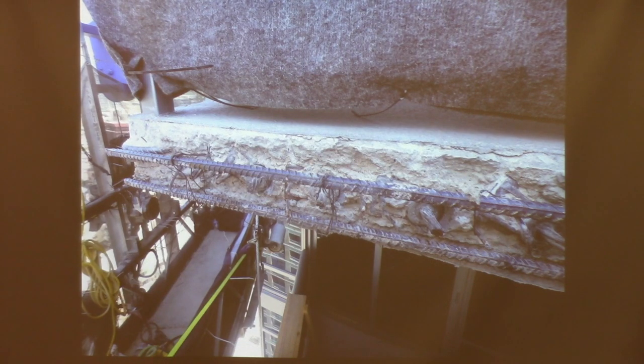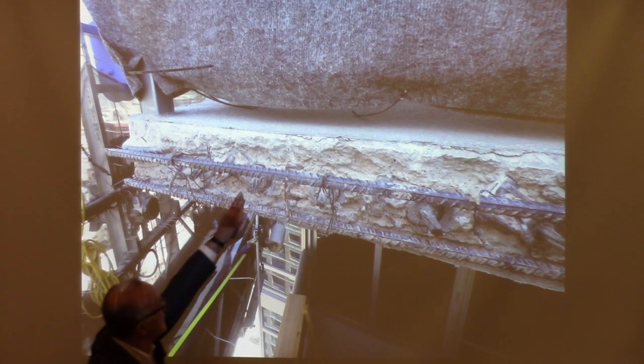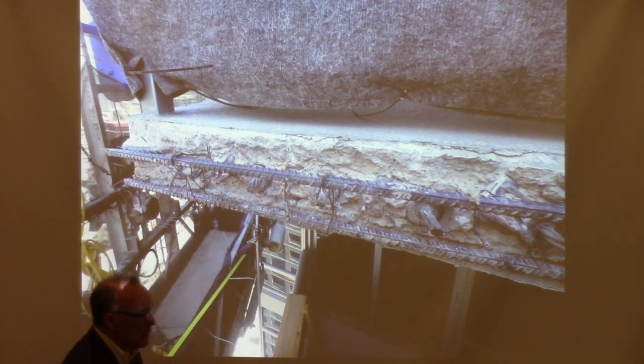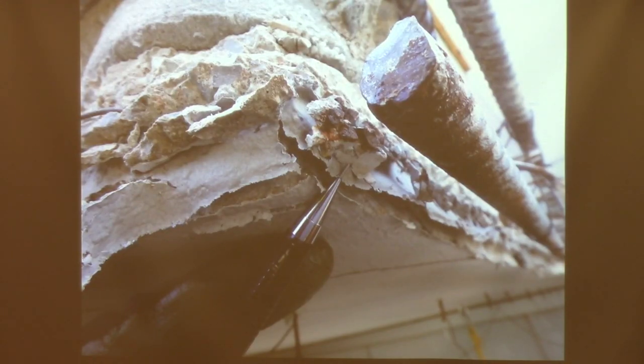Here's the chipping that was done. You can see some of the anchorages in here. Again, you have to be very careful, but the contractor that was contracted to do this is very skilled in working around post-tensioning. You look at the reinforcing steel, if the bars could have an inch or at least a half inch cover, they would remain in place. If they didn't, they were cut out and replaced. These are the types of things that we would see.